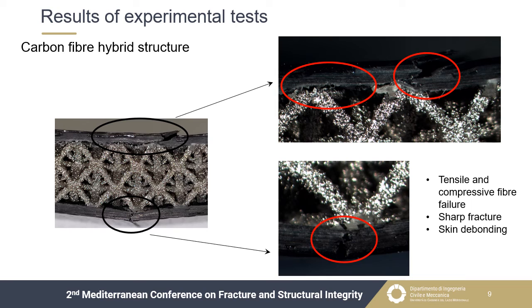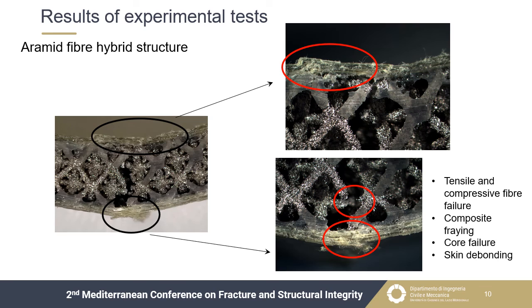As concerns the carbon specimens, the fiber failure was observed on both the upper, just below the loading nose, and the lower surfaces. In particular, the former showed a compressive fracture, while the latter a tensile one. The most interesting thing to highlight is that a skin detachment was observed on the upper surface, and the core was not damaged. As concerns the aramid specimen, also in this case the fiber failure was observed, as for the carbon one, together with the skin detachment in the upper zone.